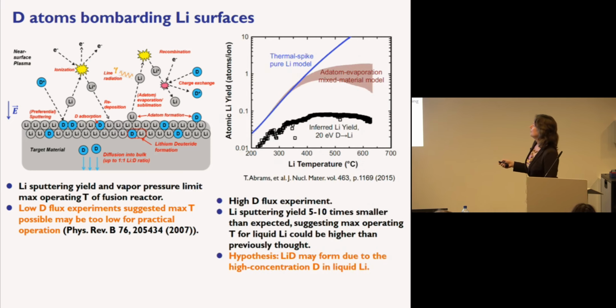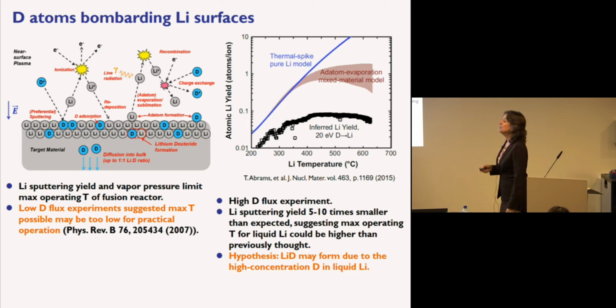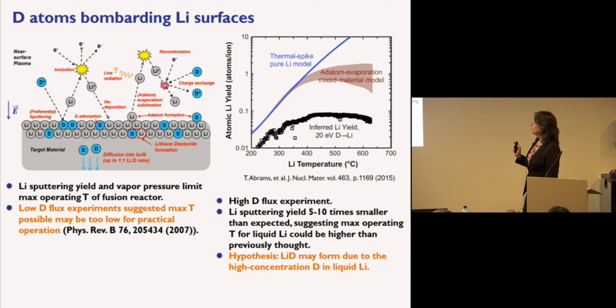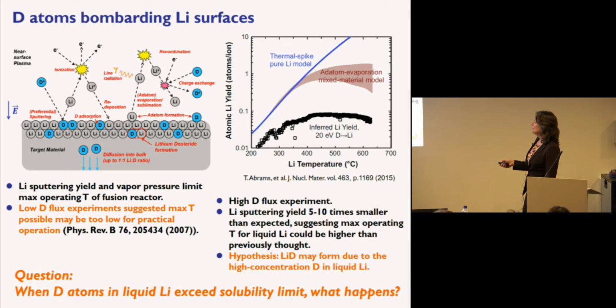Then experiments were done at high deuterium fluxes, and they had expected, based on various models and the low flux experiments, to get much higher sputter yields. This is on a log scale as a function of temperature, but in fact what they saw is a much lower sputter yield. And so the question was, why was that happening? One hypothesis was that maybe lithium deuteride is forming due to the high concentrations of deuterium in liquid lithium. So we started to look at that, and the question is, what happens when deuterium exceeds the solubility limit in liquid lithium?